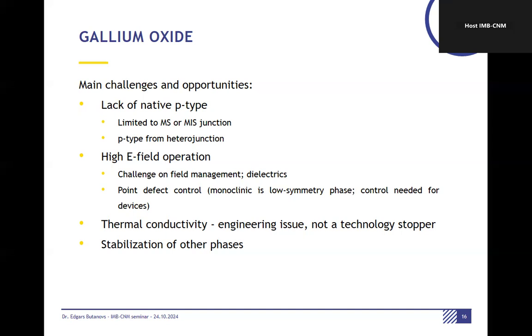Another thing: a lot of people, less now, but a few years ago, were saying, oh, the bad thermal conductivity is a technology stopper for gallium oxide. But as I've seen in the latest conferences, it's really more of an engineering issue, how to do the architecture of the device, not really a technology stopper. So there are some ways to extract heat from gallium oxide. As well, an interesting topic in my opinion is stabilization of other phases. As I mentioned, this metastable corundum alpha phase has a wider band gap, so there are some interesting possibilities there to explore, and it has not been explored that much.